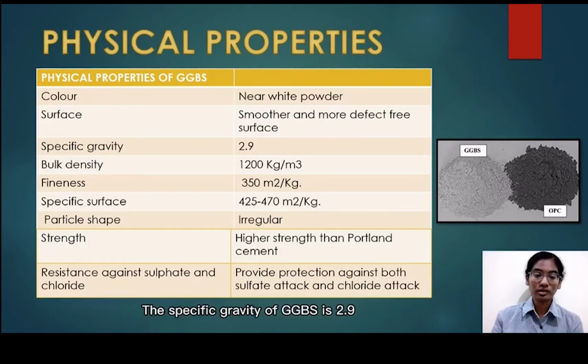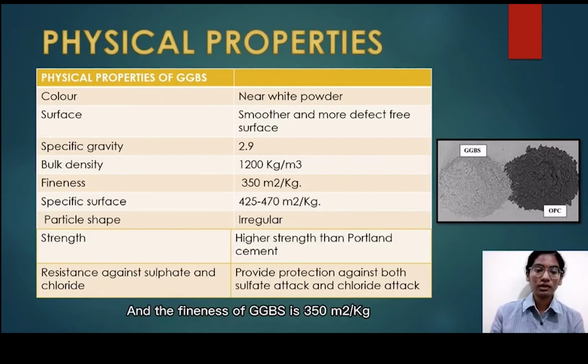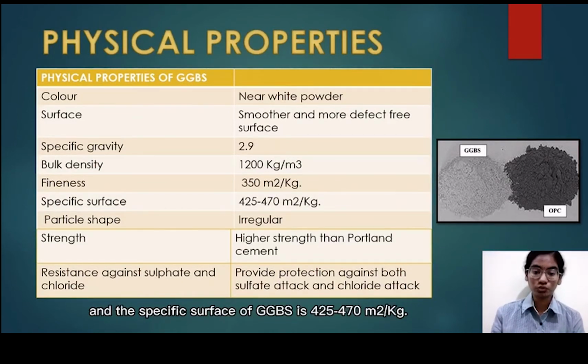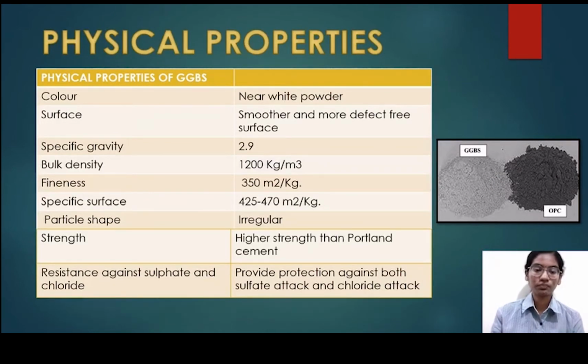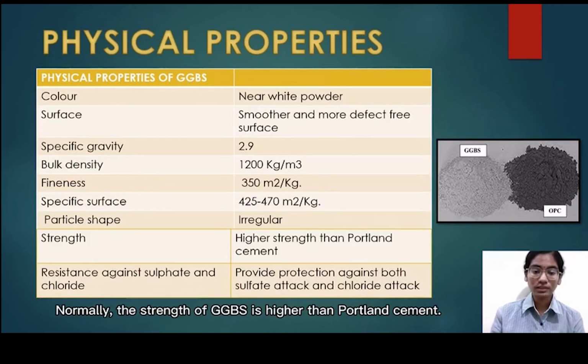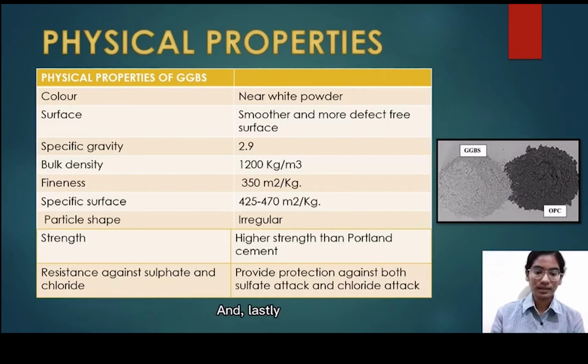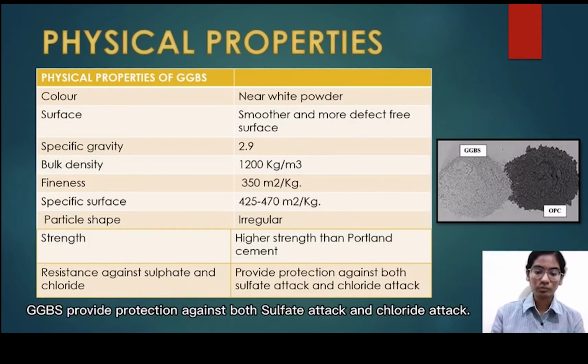The specific gravity of GGBS is 2.9 and the bulk density of GGBS is 1200 kg/m3 and the fineness of GGBS is 350 m2/kg and the specific surface of GGBS is 425 to 470 m2/kg. The particle shape of GGBS is irregular. Normally, the strength of GGBS is higher than Portland cement. And lastly, GGBS provides protection against both sulfate attack and chloride attack.